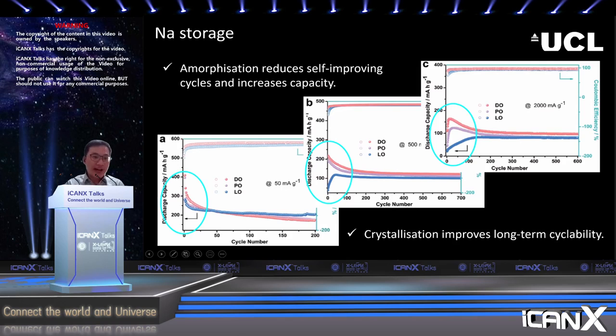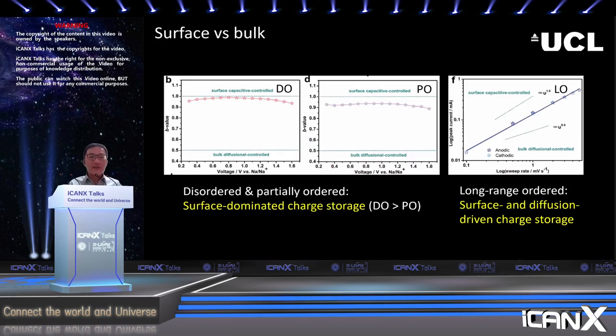We also identified the storage sites of sodium ions in the three samples. What we found is that for disordered, which is amorphous material, and partially ordered titanium dioxide, the storage process is dominated by the surface of the material. And for the crystalline titanium dioxide, which is the long-range ordered material, both surface and bulk diffusion-driven charge storage processes contribute to the capacity. So it tells us that by utilizing the defects that exist in the amorphous structure, we're able to shift the storage of the sodium ions from bulk to the surface.